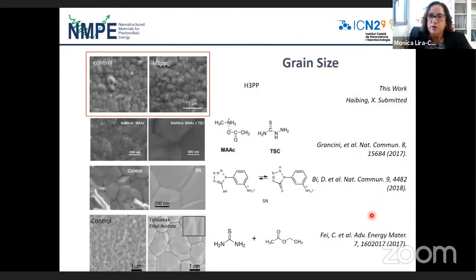We also analyzed our nanocrystalline structure, and we observe that we have small grain sizes, as you can see here. This is very interesting because most of the papers, what everybody was trying to do initially, was to play with these additives in order to increase the crystal size of the halide perovskite. If you increase the crystal size, you are producing very high quality thin films with less defects. That's what people were trying to do. In our case, however, our grain sizes were not as high as everybody else was looking at.